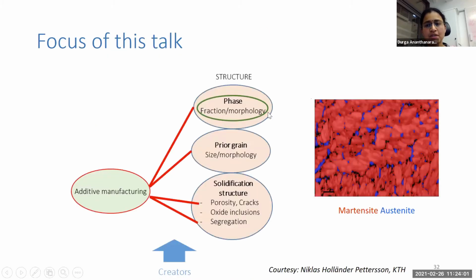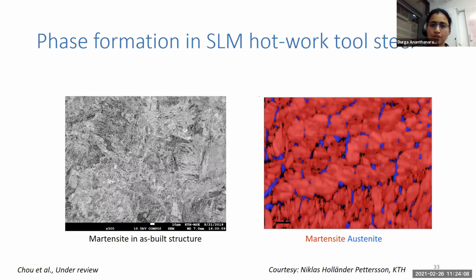Next, going to phase fractions and morphology. For this, I'll take the example of this SLM hot work tool steel that we are working with in our group. Here we see that the as-built structure contains mostly martensite and some amount of austenite in the intercellular region. So we want to be able to predict these phases forming after solidification and further solid state phase transformation.